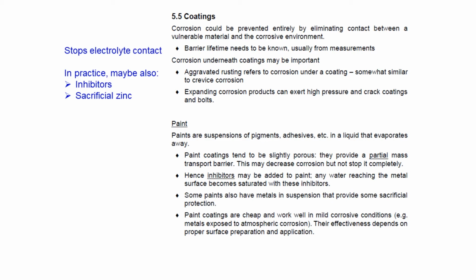Something specific to corrosion that you need to know about coatings is that you can have sometimes a partially detached coating actually as a problem, because it creates an environment very similar to the one which allows crevice corrosion to happen. If you have corrosion taking place in the same way as crevice corrosion quite severely but under a coating, then it's often called aggravated rusting.